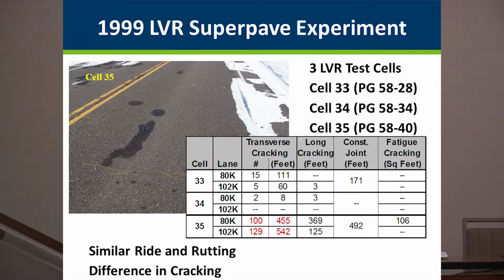So when we started getting smarter after we learned these different cracking mechanisms taking place, we built three test sections on our low volume road. So we said, we're going to show how these PG grades can really help out the state of Minnesota and northern tier states. And we built three test sections, 33, 34, 35. What was interesting about it is we thought the minus 40 is going to be the godsend, the Cadillac of oils. But we found that you can use a minus 28 and you get your typical thermal cracks across the road.